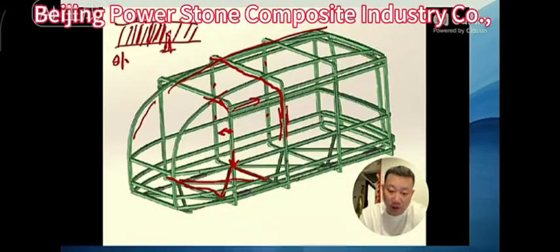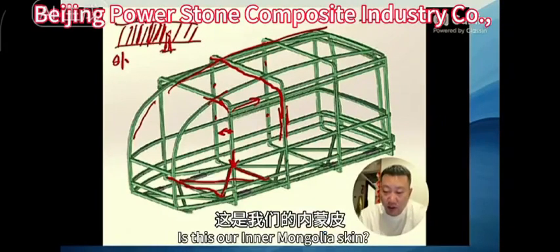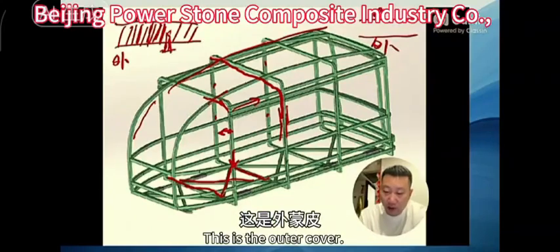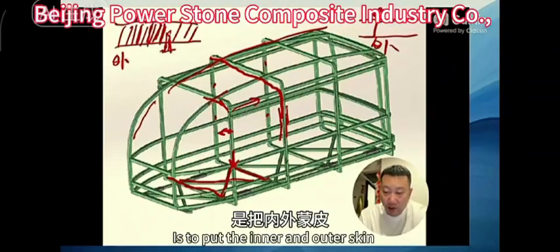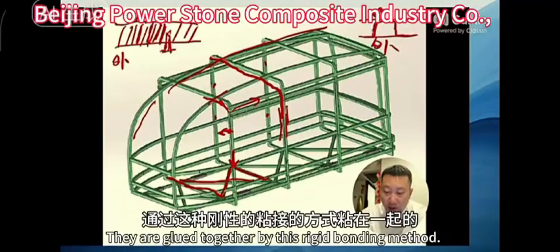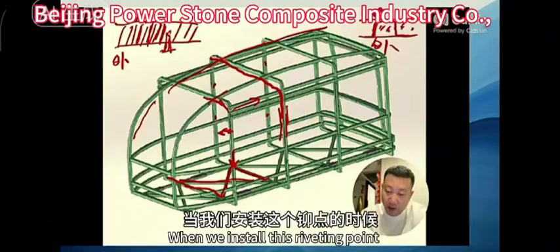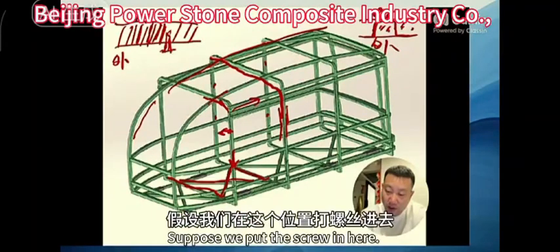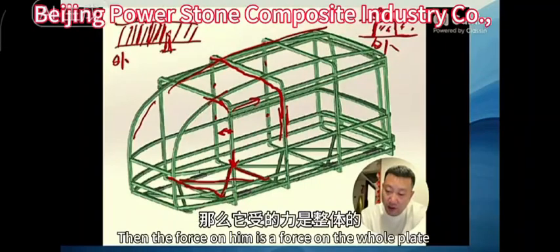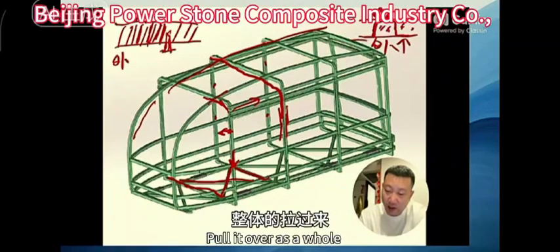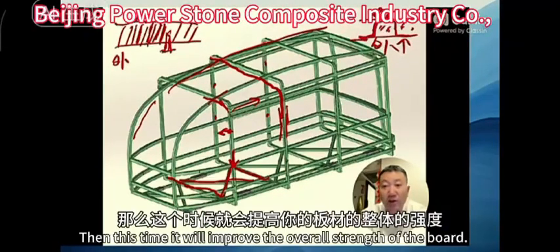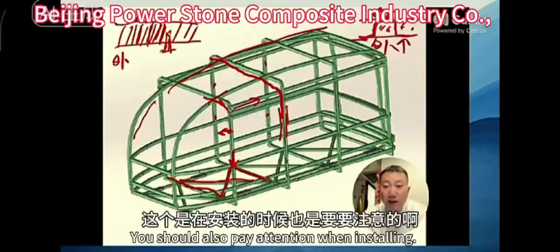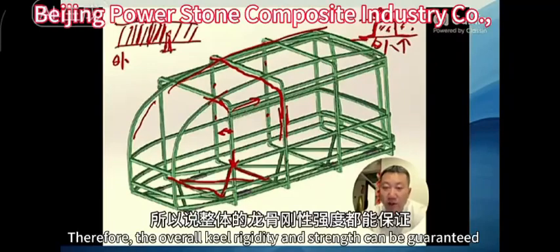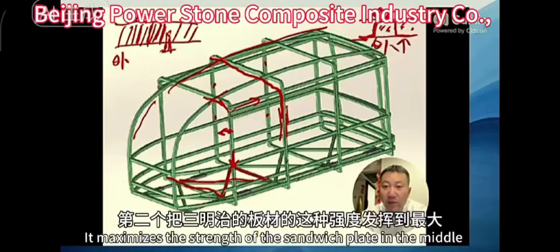On the contrary, our structure is made like this. This is our inner skin. Our keel structure bonds the inner and outer skins together in a rigid way, and the middle is the foam. When we install an anchor point, suppose we drive screws into this position, the force it receives will be applied to the entire sheet and pull it as a whole. At this time, it will improve the overall strength of the plate. So the overall rigidity and strength of the keel can be ensured. The second is that it plays the strength of the sandwich plate to the maximum.